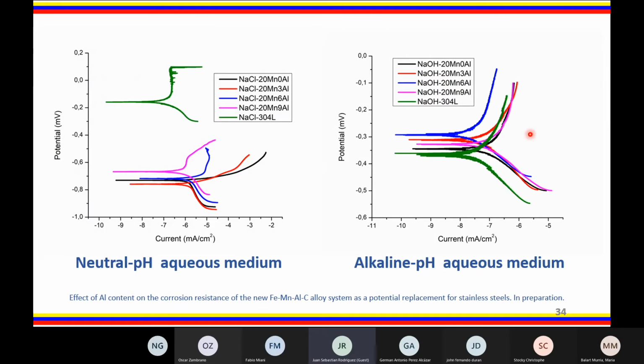In the neutral medium of sodium chloride, 3.5% by weight, it is observed that there is no great difference between FeMnAlC steels in terms of corrosion resistance, and that, on the other hand, stainless steel is still much better. But in the case of an alkaline medium, the situation is a little different. Here we can observe that the behavior in this medium is very similar between FeMnAlC steel and stainless steel. Finally, regarding corrosion resistance, it is stated that the effect of the aluminum oxide layer is not versatile, and its behavior depends a lot on the pH of the medium.